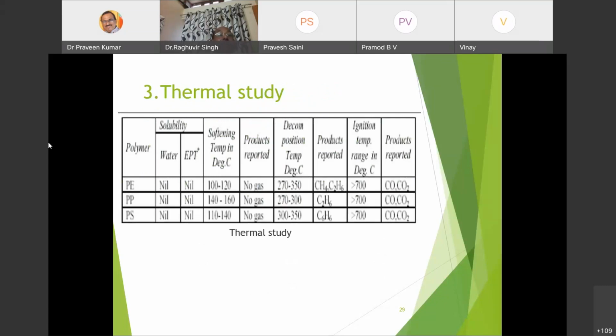Sir, there is some thermal study of plastic waste that shows the polymer, solubility, softening point, decomposition temperature, ignition temperature and products reported. For polymer PE, the solubility in water is nil, softening point temperature is from 100 to 120 degrees centigrade, and no gas is produced. The decomposition temperature is 270 to 350 degrees centigrade, with the products reported being methane and ethane gas. The ignition temperature is more than 700 degrees centigrade. The same applies for PP and PS.